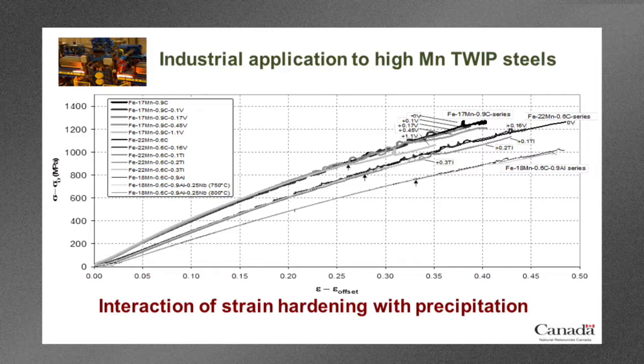But what I would say is that the flow curves tend to superimpose. So as you're adding titanium, vanadium, or niobium, you don't really seem to be changing much the strain hardening mechanisms until you get to some very high compositions. So I've tried to indicate those with the little black arrows, where the actual flow curves tend to diverge and they tend to saturate. So that would suggest that at these higher strains, we're actually changing the hardening mechanism.